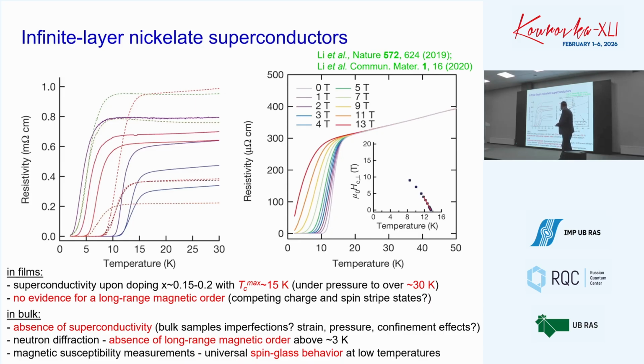What is surprising is that superconductivity appears only in thin films, although in bulk there is no evidence at all. I mean, there are nowadays very nice bulk samples of infinite-layer nickelates, doped and undoped, and all of them showed no evidence for superconductivity. Another story is the long-range magnetic order, in contrast to cuprates. Is there a long-range ordered state which we suppress with doping, and it leads to superconductivity? No evidence at all. All these materials, thin films and bulk, show none for the moment.